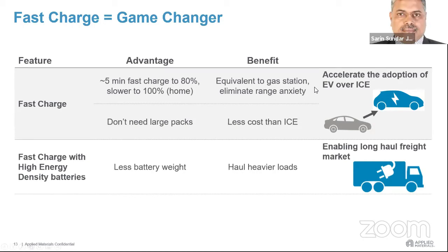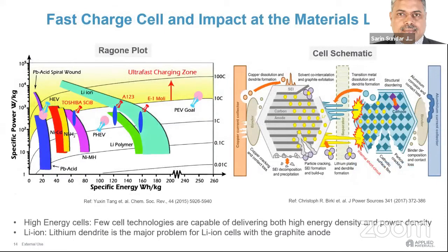Yeah. So what we are doing right now in fast charge is we can't have large battery packs. It has to be at least you can charge 100 kilometers within 5 to 10 minutes. That's what we are looking at. And if you look at some basic chemistry, existing graphite anodes cannot be fast charged, because it cracks up in the SEI layer, it forms dendrites. So most of the companies, what we say are DC charging or fast charging, are primarily using carbon anodes, or practically it's not real fast charging.